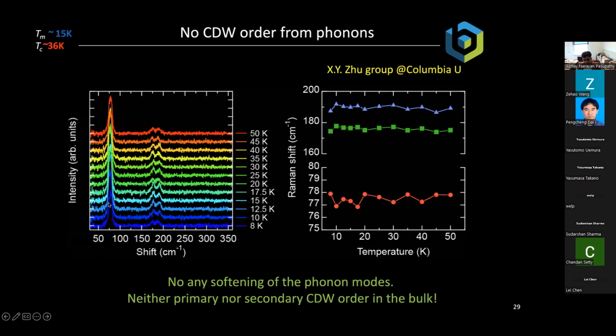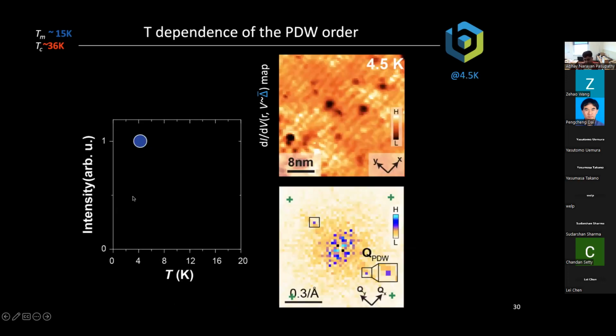So these are Raman spectroscopy measurements. Typically when you have charge density waves or other types of density waves, you see evidence for this in how the phonon modes of the crystal change as a function of temperature. And from this material, we can see that the phonon modes are basically unaffected by the presence of magnetism. And so we believe that there's really no charge density wave or spin density wave order that onsets at this temperature. Okay, so now we want to ask, how does this unidirectional stripe order change as I go through the magnetic transition temperature?